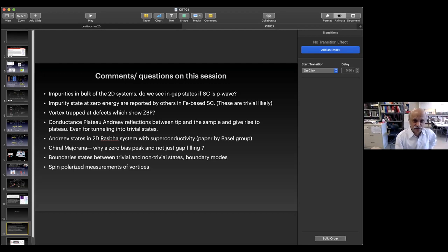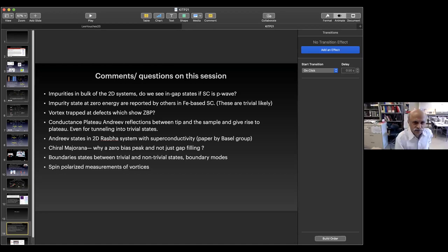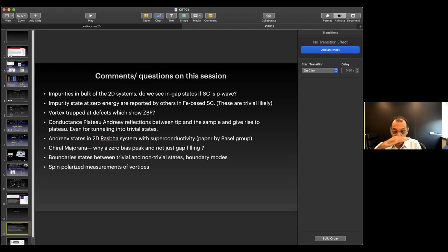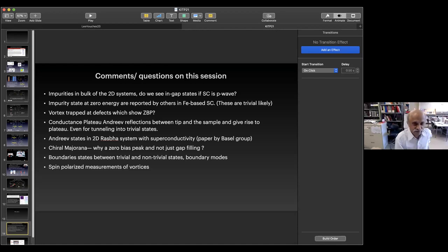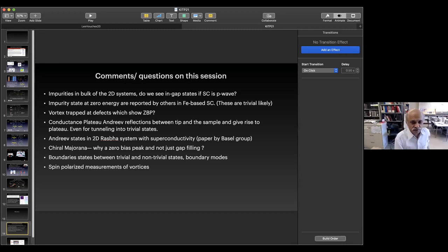So for this kind of nanowire, your chemical potential has to be... I'm just trying to get the picture. You have 5 1D modes, and your chemical potential has to hit the odd number of them. What's the separation between these modes in energy? That I do not know. It has to be an odd number, otherwise it's very unlikely, right? Yes. It's about 30 milli-electron volt from the surface band bottom.